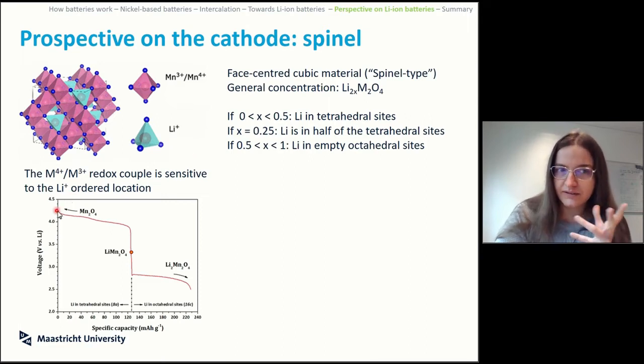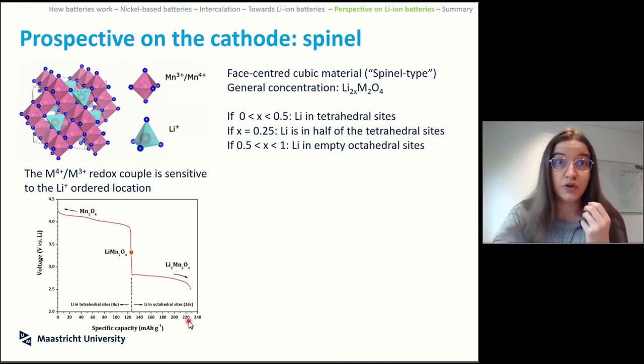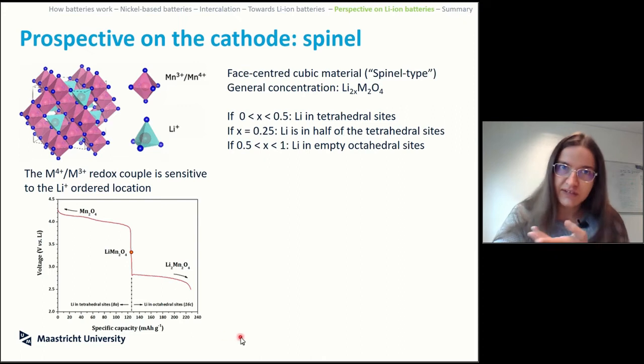you can go basically from 0 lithium with manganese 2 or 4, close to here. You start to add lithium, you get to this point of lithium manganese 2 or 4, but you can see that whereas here you have your 4 volt and specific capacity, this will go higher in specific capacity because you are increasing the level of lithium that is inside. But at some point you see that, experimentally speaking, the voltage drops. So if you keep adding lithium inside, something is happening in your structure that drops the voltage. So something is changing in the energy states.